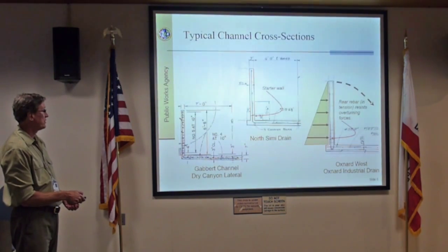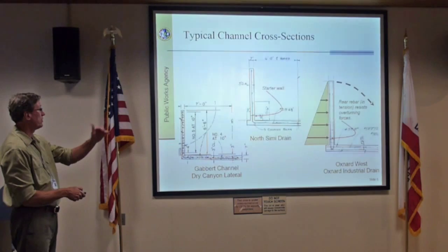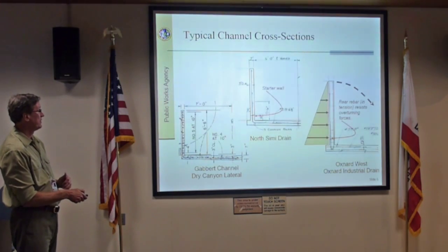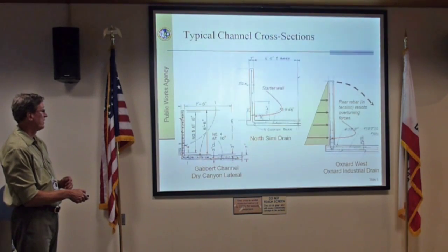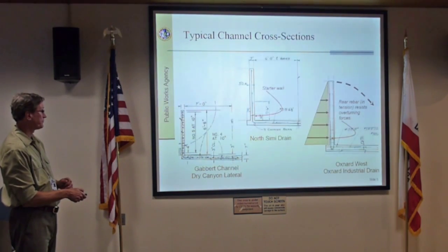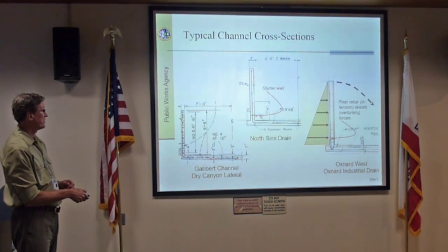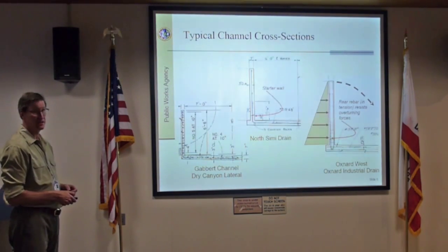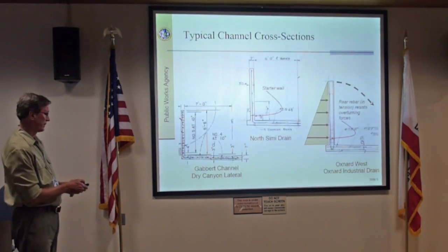So corrosion of this steel, if this was to lose its strength, then what's preventing the wall from collapsing? It's really just the weight of the wall, friction at the joint. There's not much holding it up. When you start to see deflection at the top, then you know the steel is most likely losing its strength.